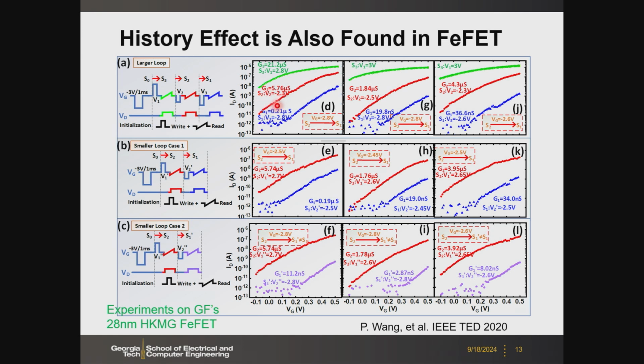So here from the red one to the blue one, we're going to apply a gate voltage like 2.8 volts to switch from here, like 5 microsiemens, to 0.2 microsiemens. And then for the smaller loop, if we want to achieve the same switching from the S2 to S1 states, then we need to apply a voltage of only 2.5 volts.